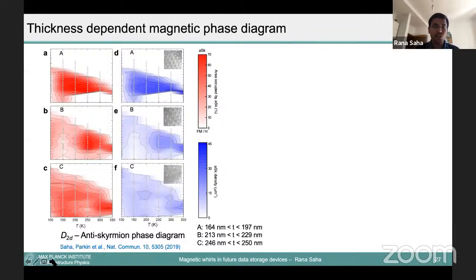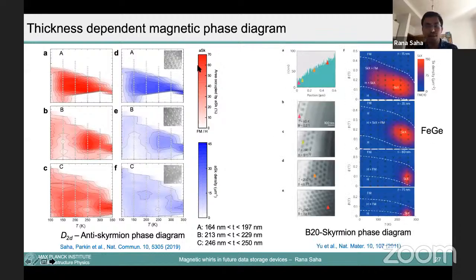And these are the antiskyrmions, and this is the skyrmion phase diagram. You can see in the case of skyrmion, this red region actually shrinks when you have higher thickness. But in the case of antiskyrmion, what happens? This thickness-dependent stability is more or less independent of the thickness because of the difference in the symmetry of these two materials, one on the left side hosting antiskyrmion, the right side hosting skyrmion.